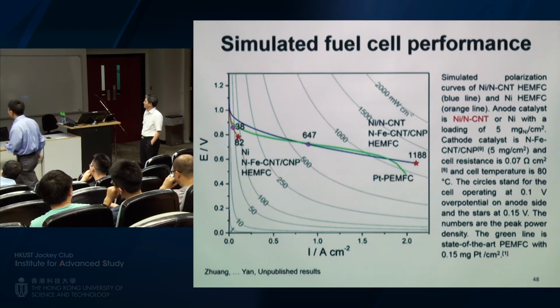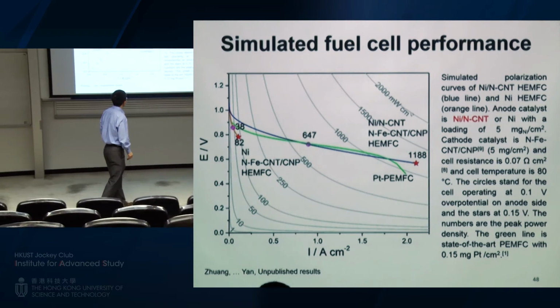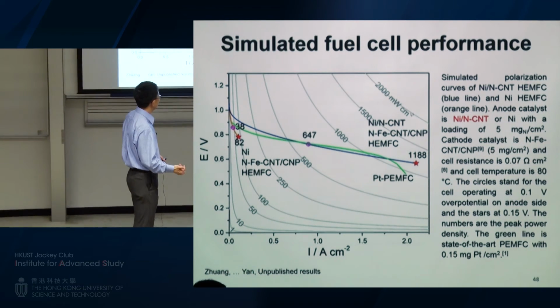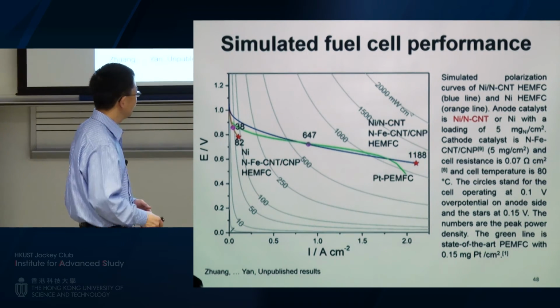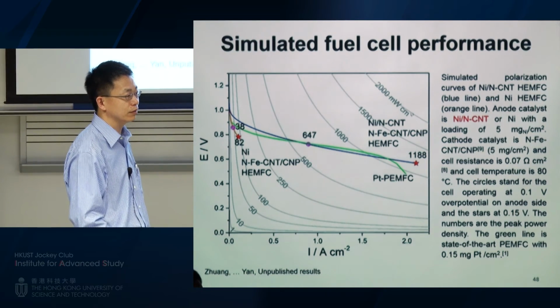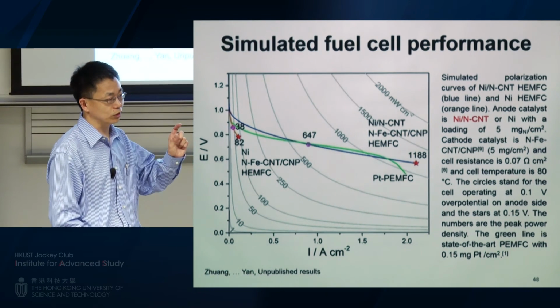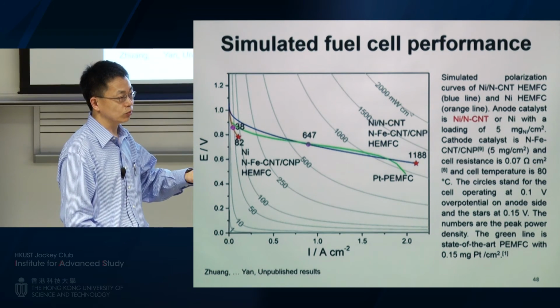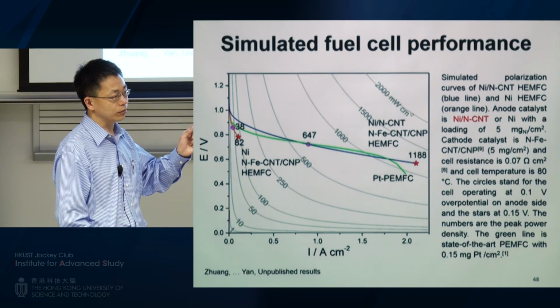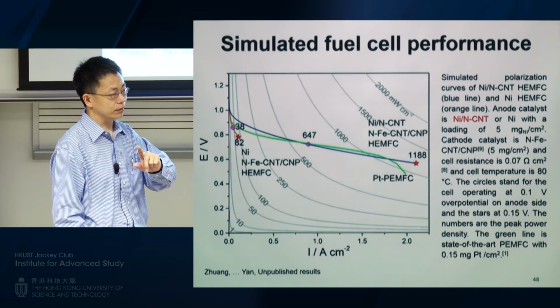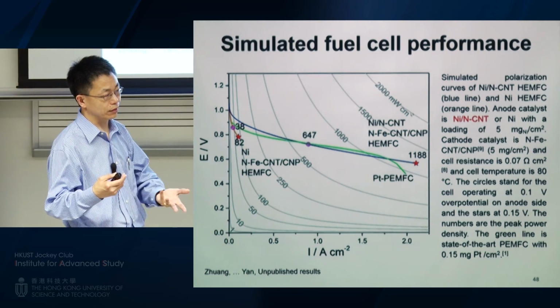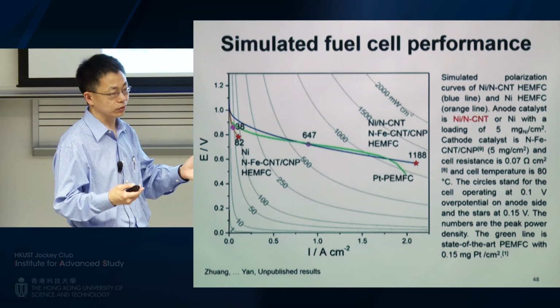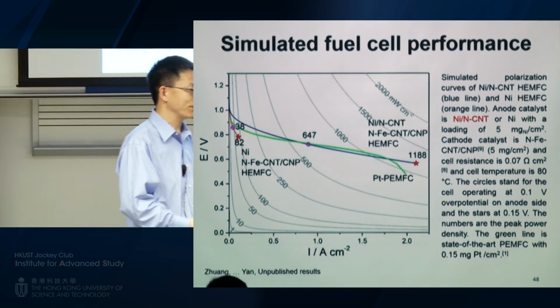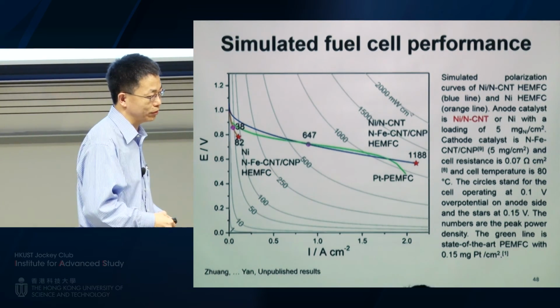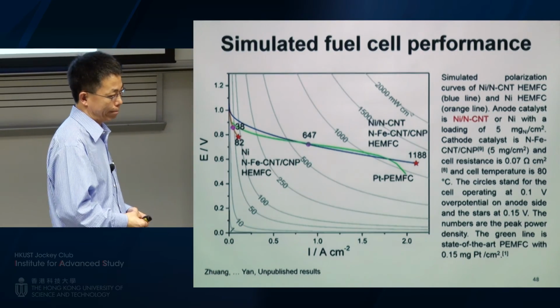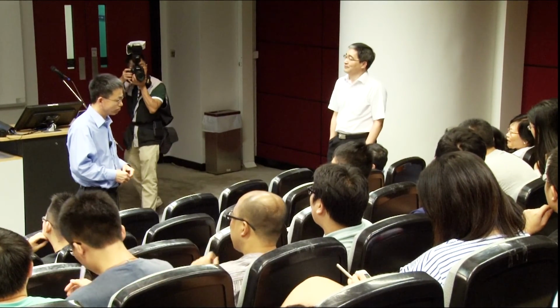Yeah. What we did in this simulation, I think we are limited by the contract. I think Tianshou actually knows. We just use the commercial membrane, standard thickness, so you know the internal resistance and published conductivity. We put it in there, and for the anode catalyst and the cathode catalyst, we take the literature data, so we know exactly the voltage-current curve behavior. It's a very simple simulation. But the short answer for the membrane is we use commercial membrane behavior or data for that.